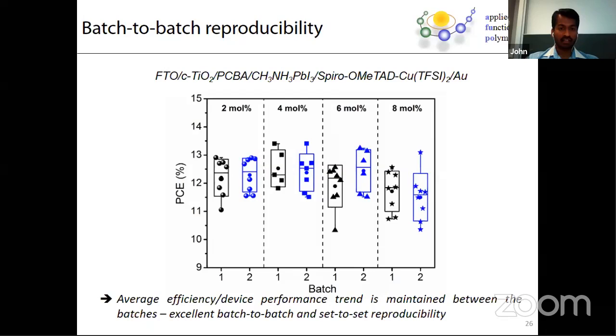So we prepared one set of batches with 2 mole percentage of copper TFSI doped spiro, prepared devices and characterized them. In a similar way, another batch, another day, another sample, 2 mole percentage of copper TFSI spiro-OMeTAD, and prepared the devices. And then we compared the end results, or let's say the performance of these devices. So in all our cases, with increasing dopant concentration, between batches, we are able to reproduce the results. So this is one of the important achievements from our side, that we are able to produce reproducibly devices with decent efficiency. It's not that we come up with a layer and that kills the entire device efficiency, but we are able to show something very decent from our side.